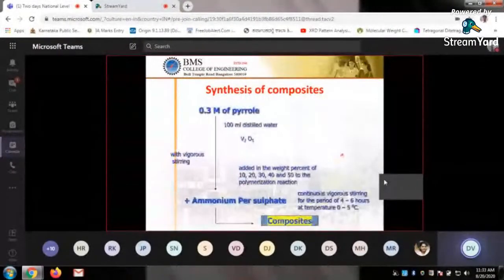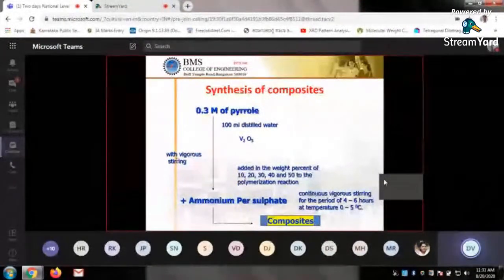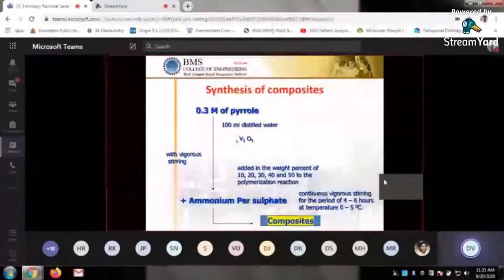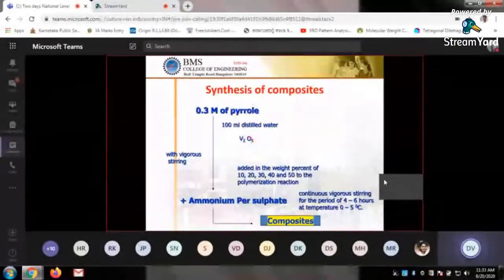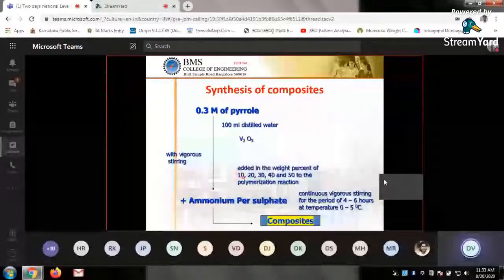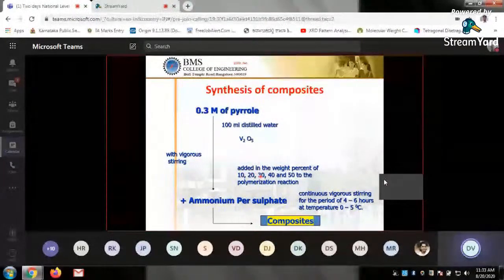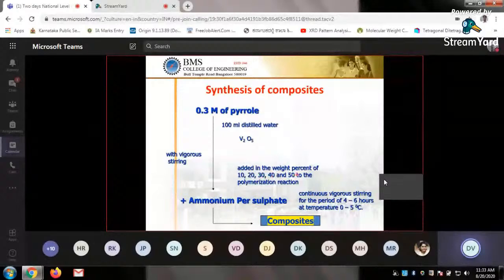Then how we are doing composites, again the same procedure. It is called in situ polymerization. Whatever dopant we are adding, here I am showing V2O5, vanadium pentoxide. Whatever dopant we want to add, you just add it to the polypyrrole itself, and then go ahead with oxidation. Once you do oxidation, you will get a composite. We are making different weight percentages of composites: 10 weight percent, 20, 30, 40, and 50 weight percent. The rest of the procedure is the same.